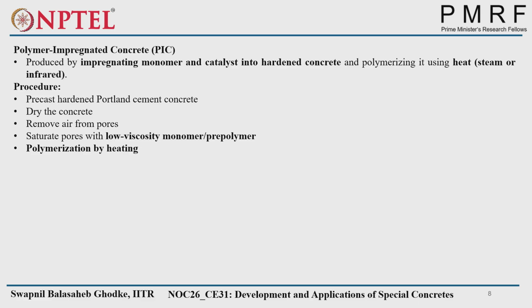Then we have to remove the air from the pores, because impregnating means we are pouring the monomer and catalyst into the pores of the hardened concrete. So to get into and occupy the whole pores, we have to remove the air from the pores. Then saturate the pores with a low viscosity monomer or prepolymer.